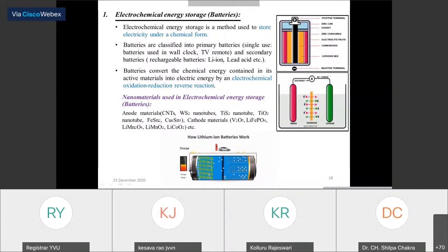So this is the function of a lithium-ion battery basically. While it is charging, the electron moves from cathode to anode, and while it is discharging, electron moves from anode to cathode. So the basic nanomaterials you can use for battery applications are CNTs and tungsten disulfide nanotubes, titanium disulfide nanotubes, TiO2, titanium dioxide as an anode material. And as a cathode material, you can use vanadium oxide or lithium ferrites or lithium Mn or lithium cobalt as the cathode materials.